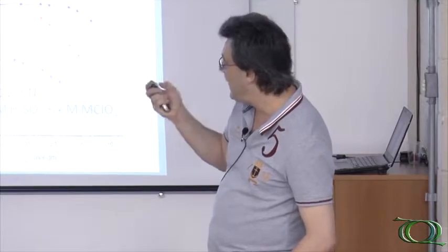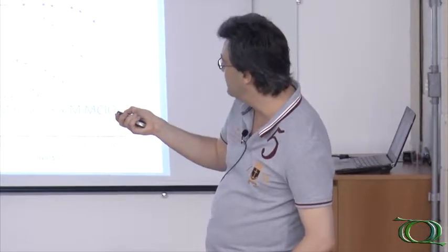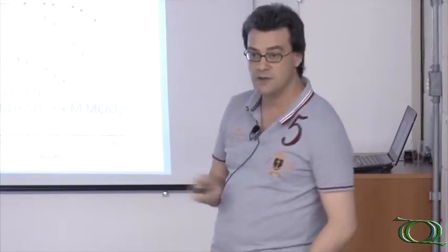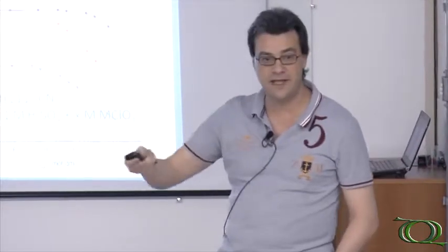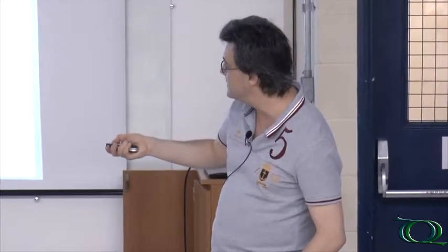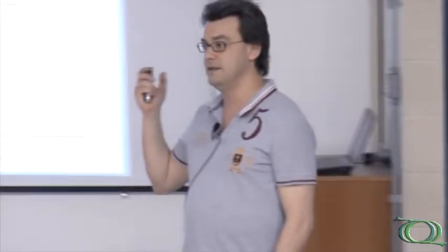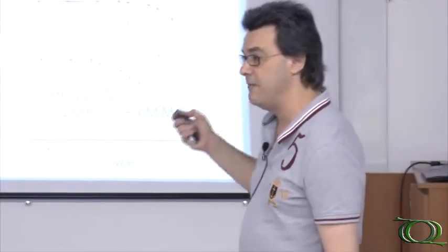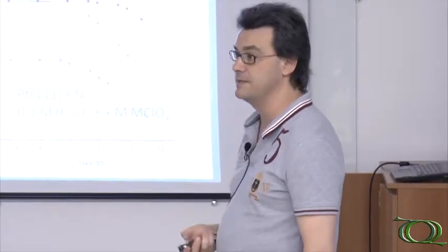So I forgot to explain. Here we have this disorder-order transition. So here we have an ordered sulfate layer. And if we increase the potential, here we adsorb some more sulfate, and the layer disorders. When we have sodium or potassium, this feature here changes quite a lot. You see here, again, we have sharp spikes. We have not looked at this with the STM yet, but I am pretty convinced that here we are having some kind of other phase transition.